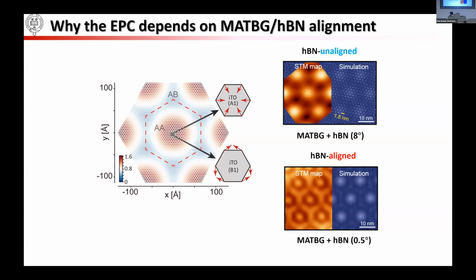Of course, if you want to study from the model point of view, for the unaligned sample, because the hBN interaction with the MATBG is weak at a pretty high frequency, it's more like a freestanding MATBG. So the K and K prime points are pretty much degenerate in energy. But if you have the hBN aligned, with this hBN moire, which can be seen clearly here, it's very strong, so the K and K prime degeneracy is lifted. If you want to scatter from K to K prime, then the cross section is much less. I think these are our current understanding.